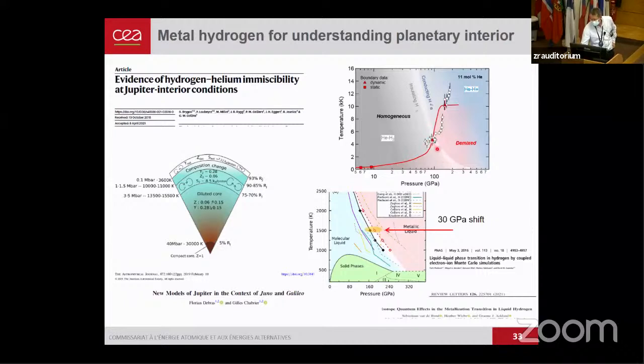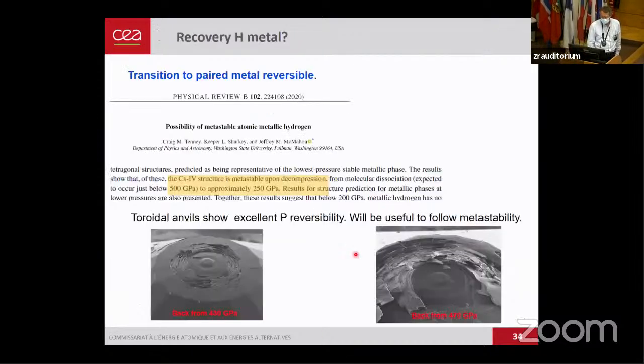What's important here is that there have been some calculations that there should be an isotopic shift between H2 and D2, even in this region of metallization of hydrogen inside the planet. And in the calculation, the isotopic shift is of 30 GPa, which is of the same amount as what we're measuring at very low temperature. So it's just an example to show you that what we are measuring on the sample to disclose quantum effects can be important to explain more the properties inside that planet.